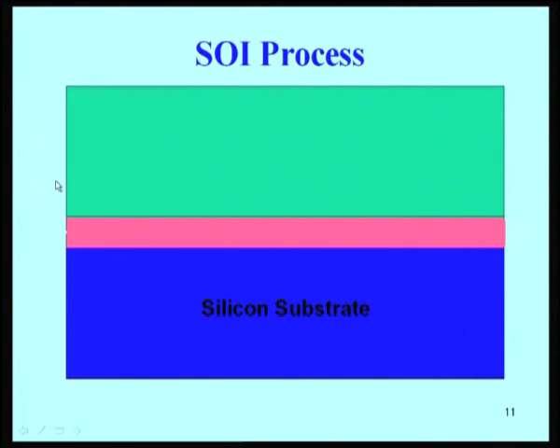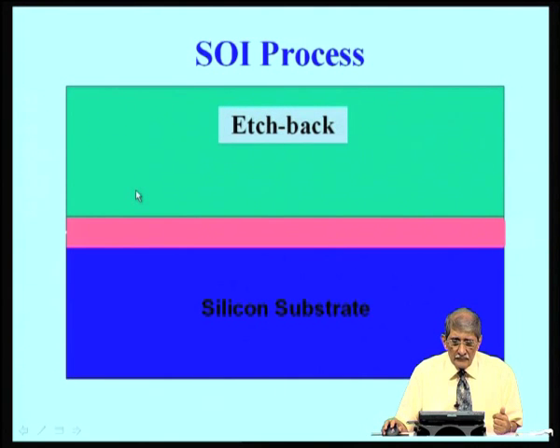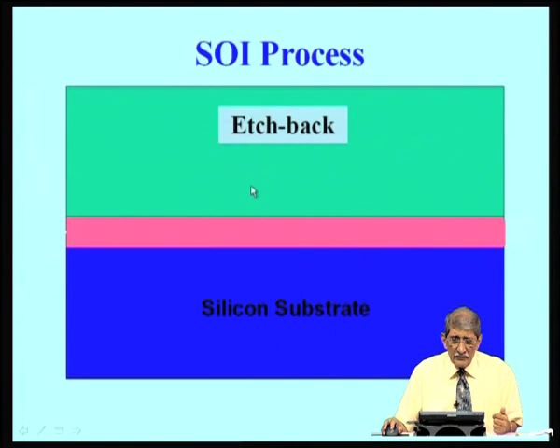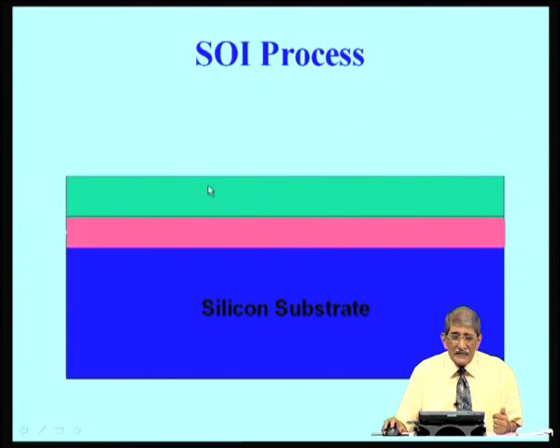Now, what you do is, I want this top layer to be very thin, so etch this, protecting the back side, etch down. Please note very carefully that portion is etched. See, from here it is etched completely, that is etch back, bonded and etched back. You call it SOI sometimes. Bonded and etched back SOI, silicon on insulator. So, you have now silicon on oxide layer, two wafers bonded together, top layer reduced to the required thickness.